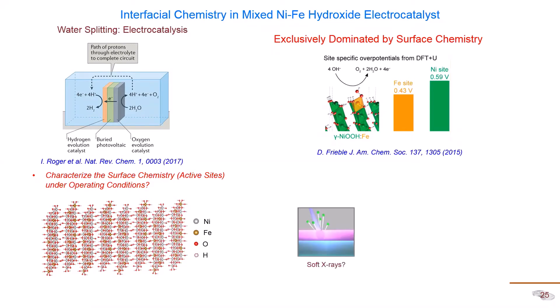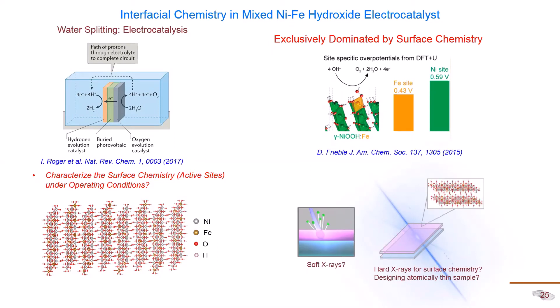From the structural standpoint, hard X-ray diffraction is not very sensitive to these small changes, but hard X-ray absorption spectroscopy can give some structural information. Looking at the pre-edge feature of the pristine material versus material charged to 1.6 V, the charged sample resembles the feature for iron oxyhydroxide — indicating iron segregation from the lattice. When we perform a recovery process — either soaking the electrode in electrolyte or performing cathodic reduction — the structure is able to partially recover, meaning iron can be put back into the lattice.